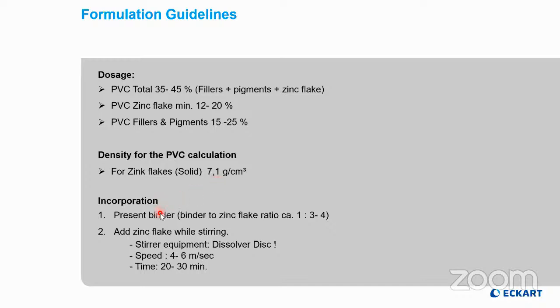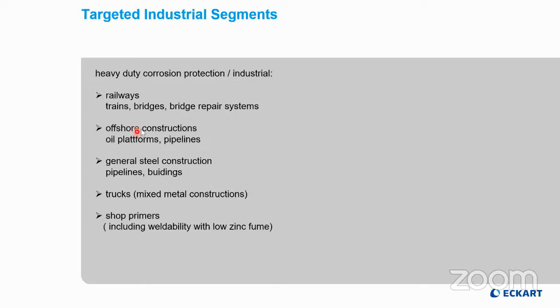The incorporation of the zinc flakes into any binder chemistry is relatively simple. You can start with the binder and add at the required ratio the zinc flakes. You need some stirring. You preferably use a dissolver disc at a speed of 4 to 6 meters per second. That equals round about 2000 RPMs. And when you do this for 20 to 30 minutes, the zinc flakes should be incorporated accordingly.